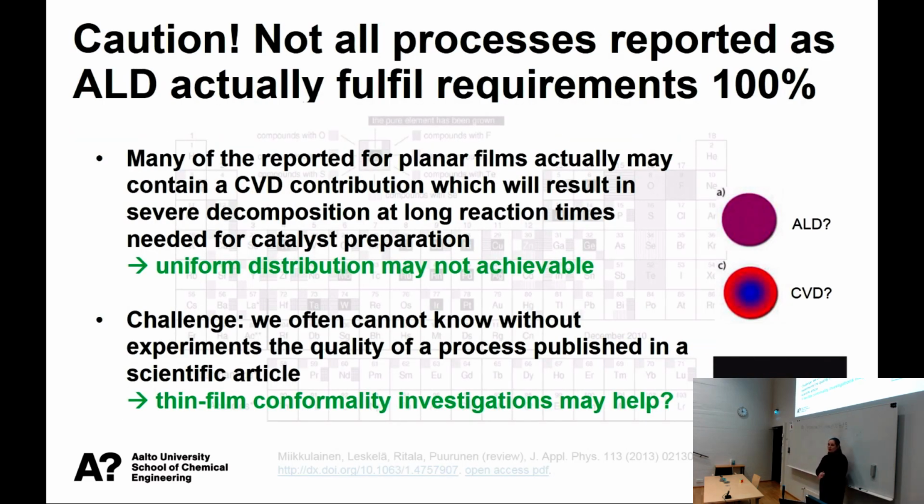And okay, so more than 700 processes have been reported, but now that we want to use them for catalysis, I myself have actually little trust that a certain process would directly be applicable for porous materials. So they have been typically tested on planar surfaces, and how well have people actually verified the saturation? The cycle times on these flat surfaces are on the order of seconds. If we want to have coatings on porous materials, it might be half an hour that we do one reaction. And if there is a slight